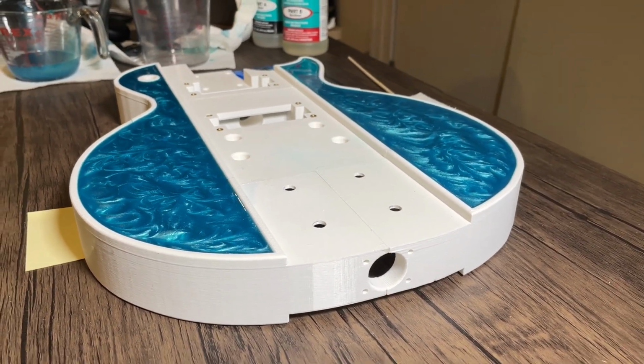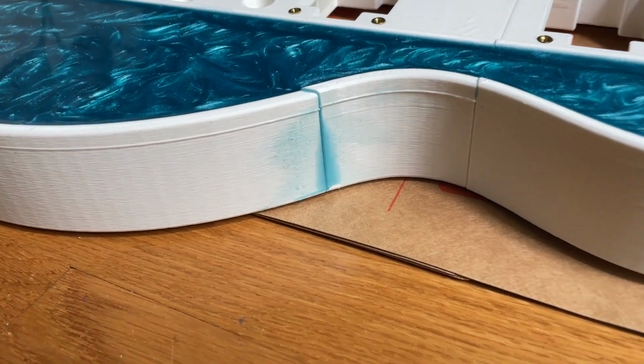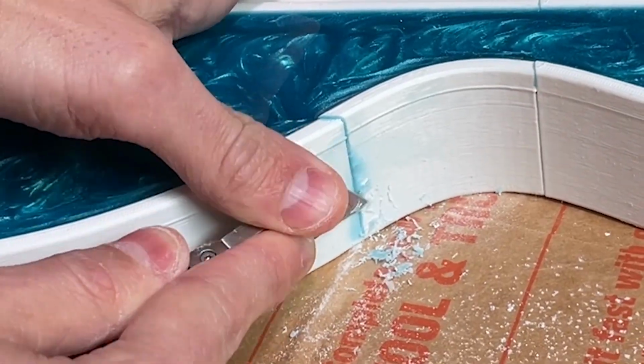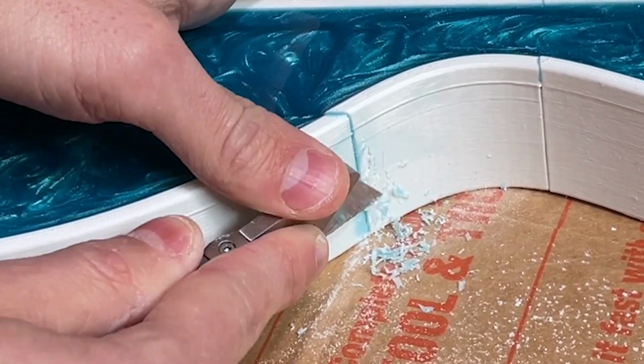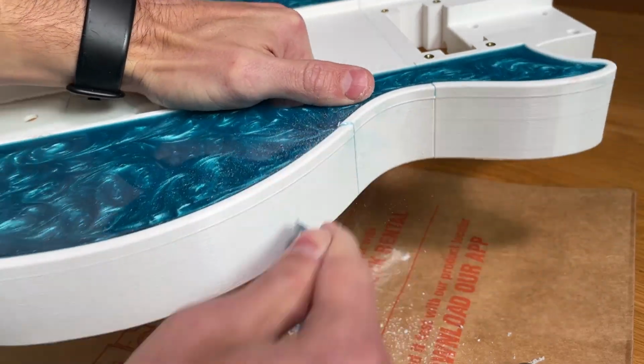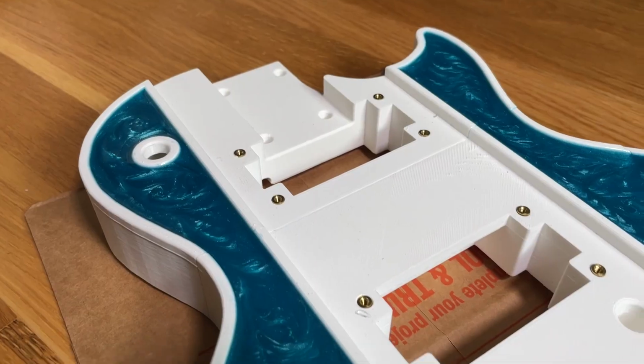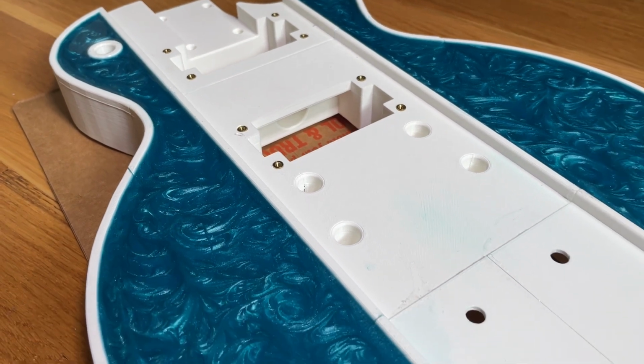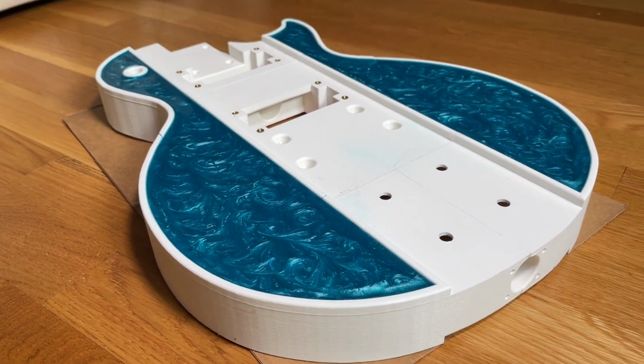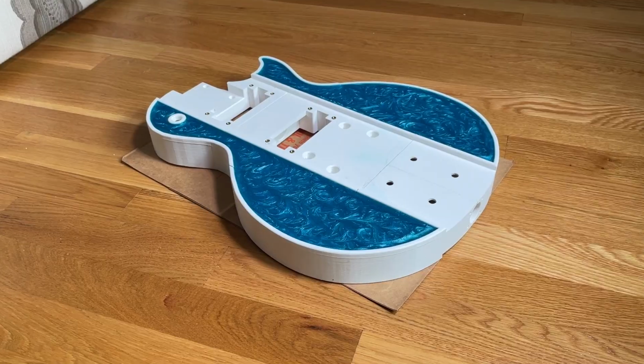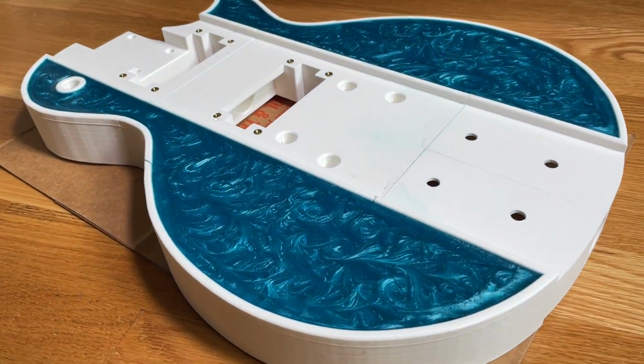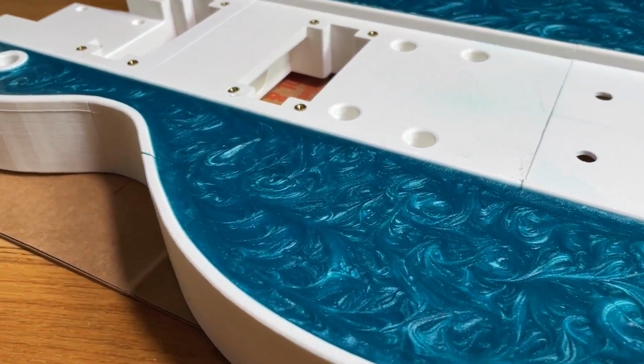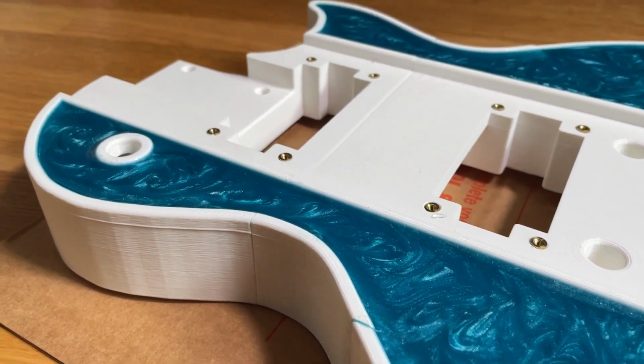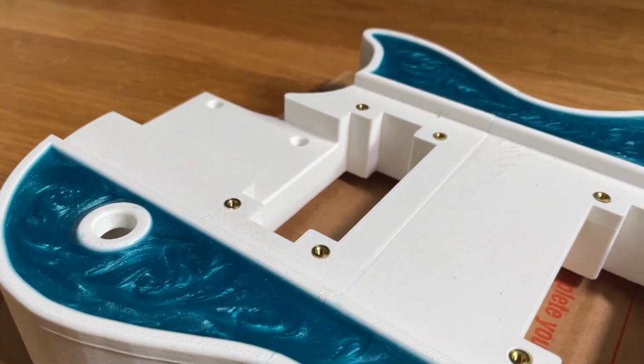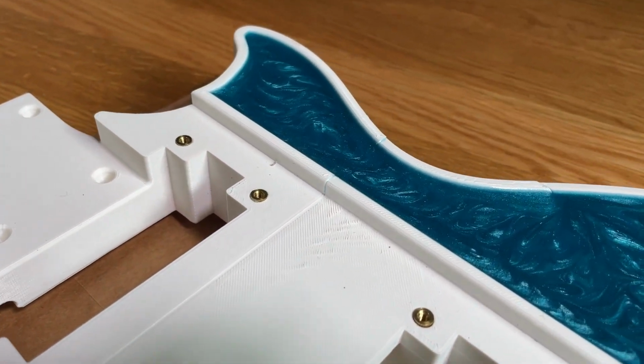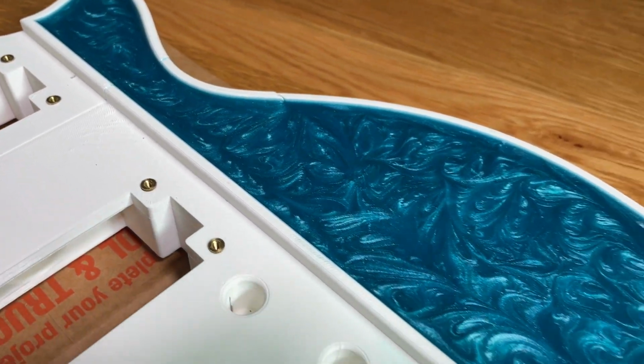One issue I ran into was a small amount of leakage between the seams. So I would recommend first sealing the seams with more PVC cement or coating them with clear epoxy prior to pouring the rest of the resin. I waited 48 hours to let the epoxy fully cure, and I have to say that I'm extremely happy with how it turned out. In addition to being nice and level, the resin added a tremendous amount of strength to the body and visually turned out even better than I was expecting. This is something I definitely plan to experiment with more in the future.